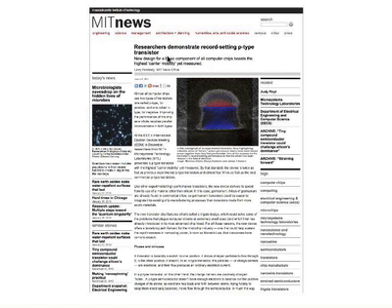All they did was make a transistor which had very fast response. In very simple terms, they increased the mobility. The way they increased the mobility was they changed the band structure of the material. In this particular case, they actually stressed the material. This is germanium. The same principle.